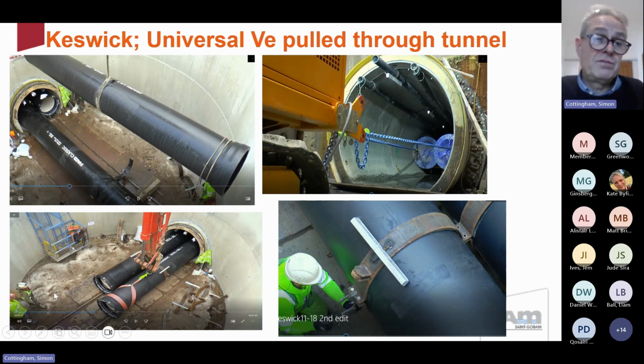As I said, the shaft here was probably about 9 or 10 meters in diameter, so not a lot of space, but just enough to lower the pipes into position. A couple of flange sockets and blank ends, and pulled everything through. The blocks here, interestingly, weren't anything to do with guiding the pipe through. This was because they weren't going to grout the tunnel up afterwards. They were going to leave the carriages in position, and these are zinc blocks to galvanically, cathodically protect the steel carriages from corrosion, so that they didn't cause the pipe to drop in the tunnel. So that was an interesting one.